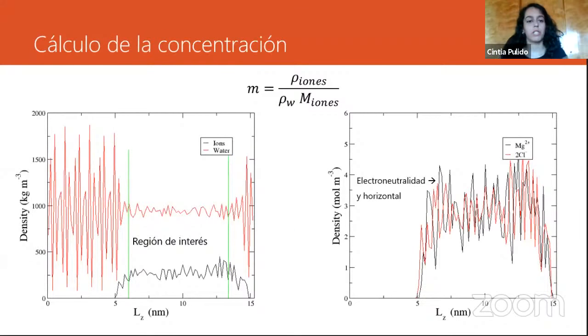It's in Spanish, but basically what we did is use the gmx density option of GROMACS. With that, we can take the density along the box for water and the ions as well. And then we identify where the ice is and where the liquid is, in this case between the two green lines. For that, we get the average of the density of the ions and the average for the water density.